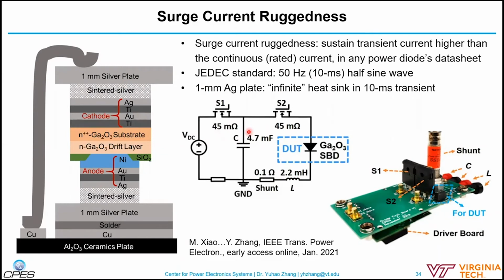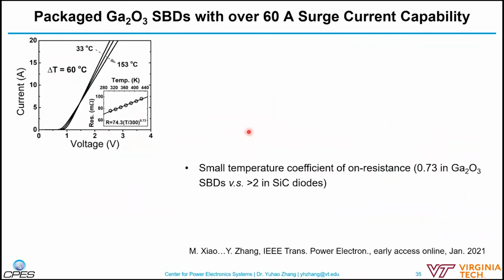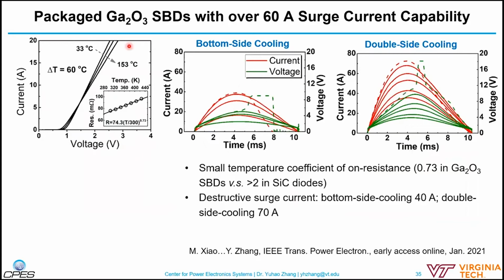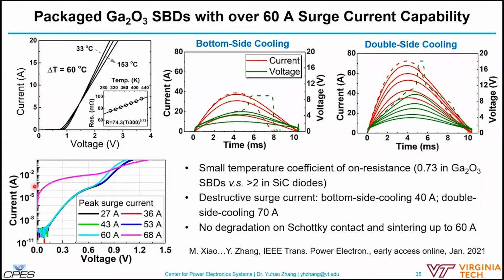So it's a little bit different from the steady state. Okay. And you see, this is the IV characteristics of our packaged devices. It can give a current up to at least 20 amps in our testing circuit. The bottom side cooled packaged device can sustain up to about 40 amps until the device failed thermally. And the double side cooled device can sustain a peak surge current up to 70 amps. And we also measure the devices every time after a single surge current test.